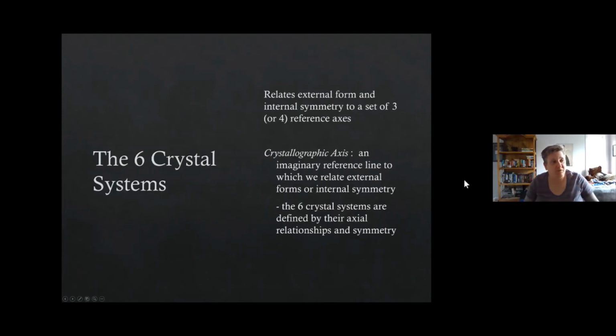So the 6 crystal systems are essentially what you'll have heard more about, if you hear it's triclinic or monoclinic, but in order to decide that, you have to know what the actual symmetry is. You can kind of tell from the outside of a crystal if you have good enough faces, but then you get things that are pseudo-hexagonal. If you look at aragonite, for instance, you're not going to look at twinned aragonite crystals, those nice ones from Morocco, and say that it's orthorhombic. If you weren't looking closely, you'd probably say that it was trigonal or hexagonal, but it's not.